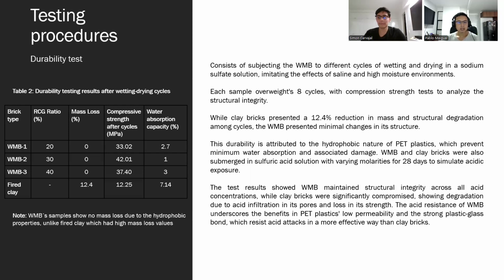Okay, the durability test consists of subjecting the WMB to different cycles of wetting and drying in a sodium sulfate solution, imitating the effects of saline and wet, moist environments. The clay bricks present a 12% reduction in mass and structural degradation among cycles. The WMB present minimal change in the structure. Test results show WMB maintained structural integrity across all acid concentrations, while the clay bricks were significantly compromised, showing degradation due to the acid infiltration in their pores and loss in their strength.